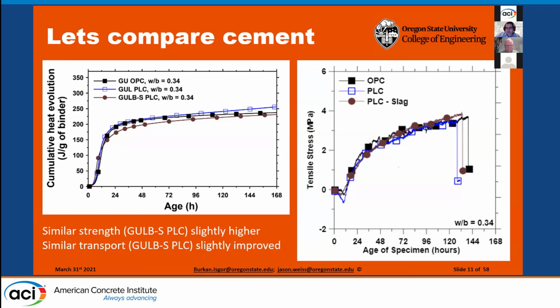Now, if we started to test those materials, and we've got reports that go into all the data, and I'm not going to go through all the data, I just want to show that in general, on the left-hand side, what we see here is the heat evolution. We see very similar heats being generated by these materials out at 7 days. We see slightly lower heats with the slag early on. There was a question: could you use slag cements to drive down some of the high heats at early ages? The answer is yes, you can do that, and that's one of the reasons why they're being used.